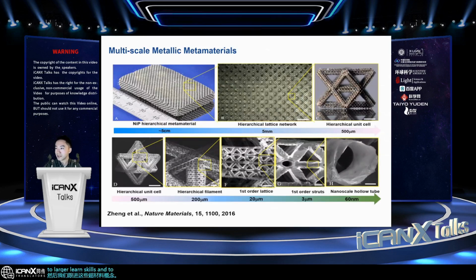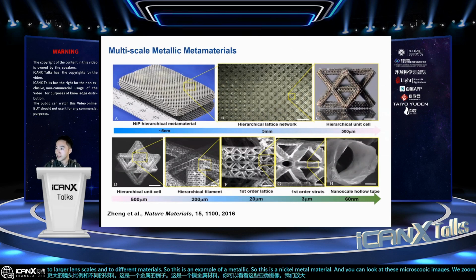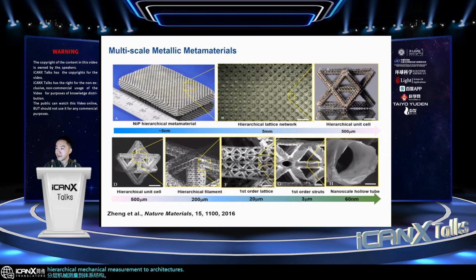This is an example of a metallic, a nickel metamaterial. And you can look at these microscopic images. You zoom in under an optical microscope, and then the row here shows the scanning electron microscope images. You can see these recurring hierarchical mechanical metamaterial architectures spanning over 7 orders of magnitude in length scale, with the smallest length scale being a few microns, with feature sizes down to tens of nanometer wall thickness of metal. And you can see this metamaterial comprised of smaller metamaterials, and each smaller metamaterial block is comprised of an array of these stretch dominated units.